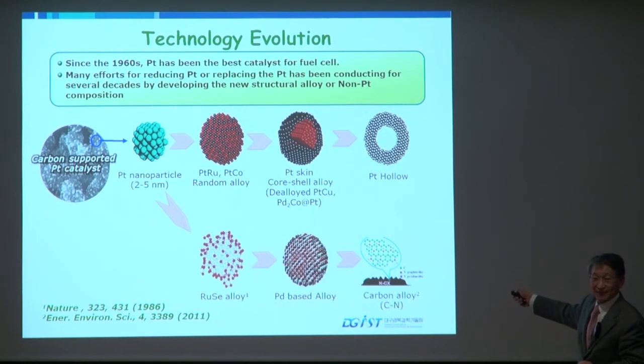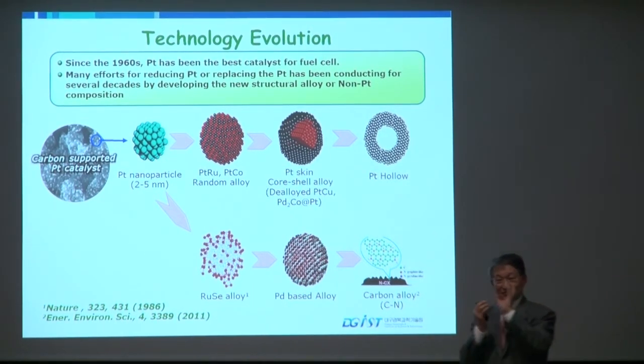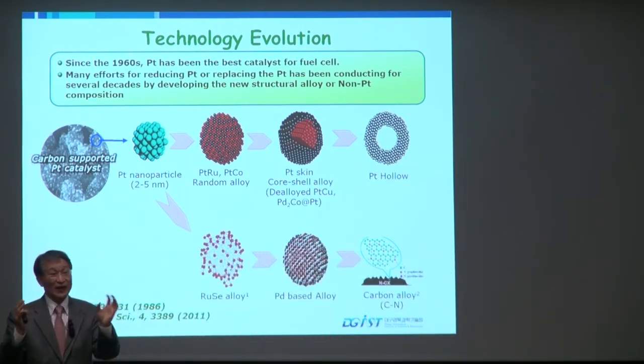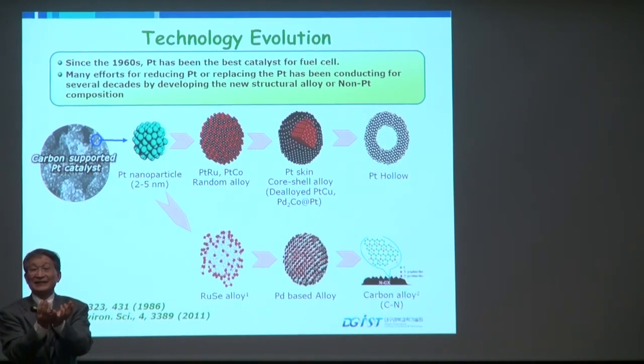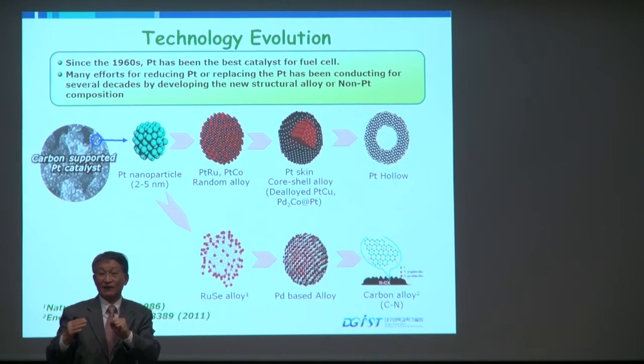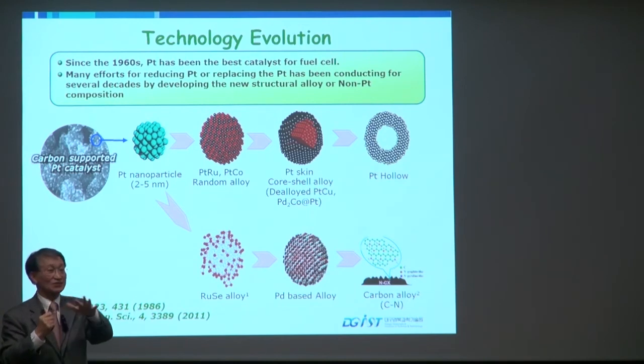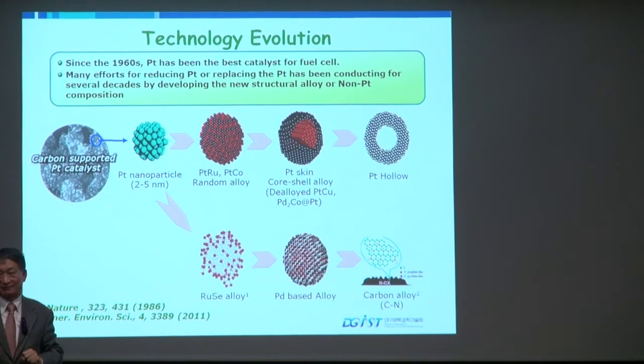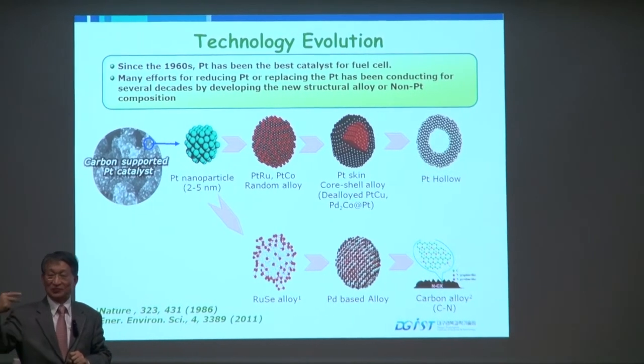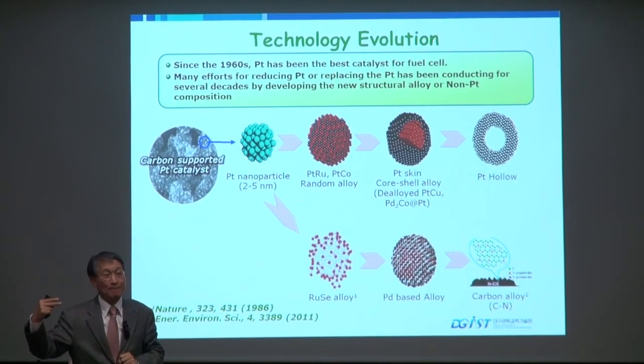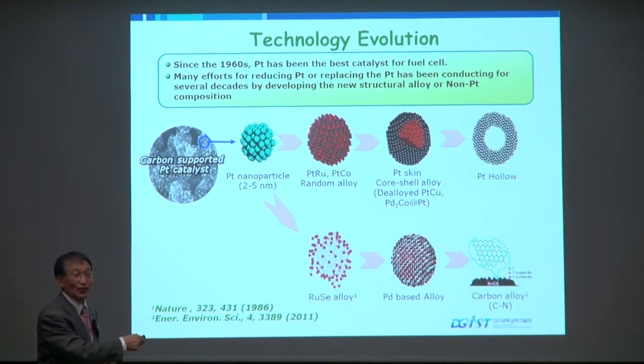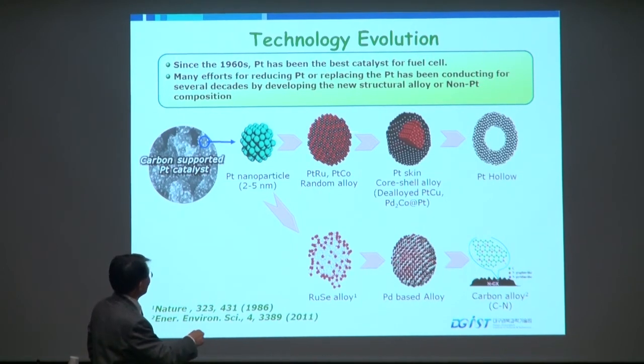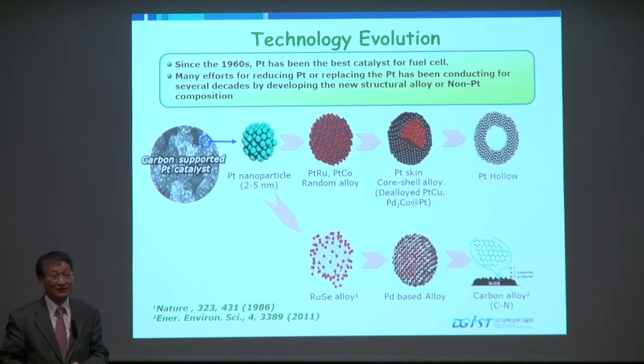Then core-shell. So have all platinum outside and some transition metals inside. And it worked fine because platinum covers the outside completely. And there is an electronic interaction between the core metal and the shell platinum, which acts favorably for decreasing the d-band structure. Maybe students do not know what d-band structure is, but it is an electronic property of d electrons which controls the bond energy of oxygen adsorption. Then hollow, without any core substrate, just a hollow shell. And from this to this, we have reduced the amount of platinum significantly.